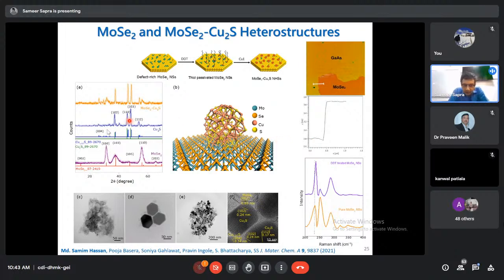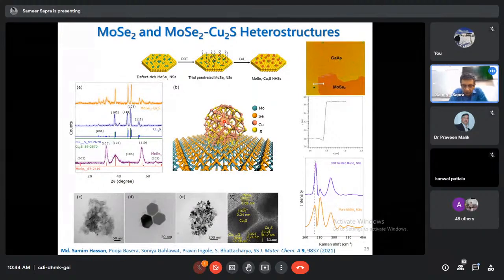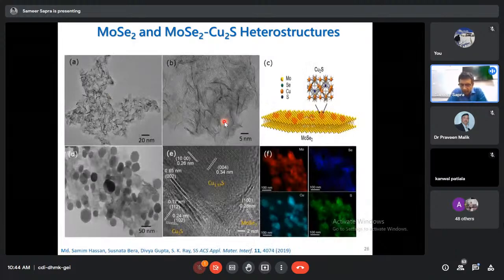Again, the XRD, of course, tells you the same thing that I've discussed. Okay, this is a kind of model where you have your defect sites occupied with sulfur. Okay, and lots of these sulfur, and then cuprous sulfide grows. So actually, we are using a slight excess of DDT so that all these sulfur molecules come in. Copper has a good affinity for sulfur, and it can very easily break the organic chain apart and grow as cuprous sulfide. Right. So some more characterization, I can just skip that.